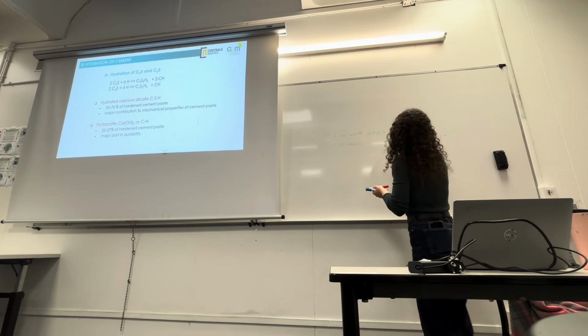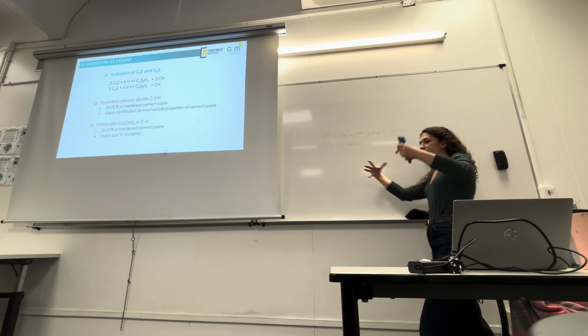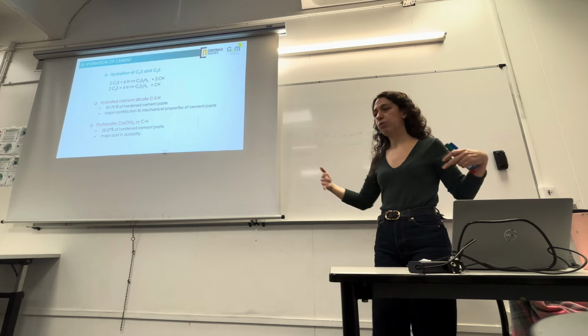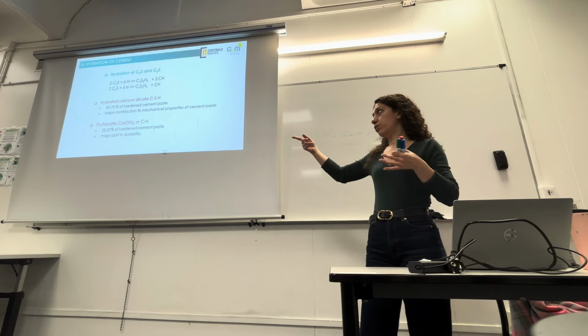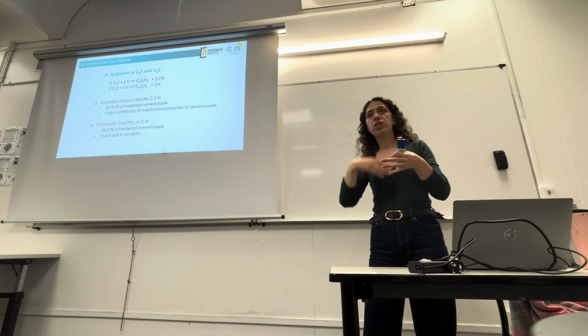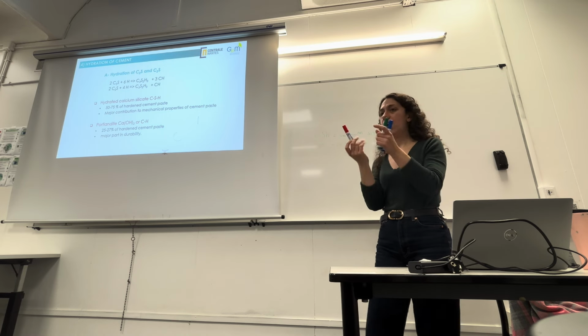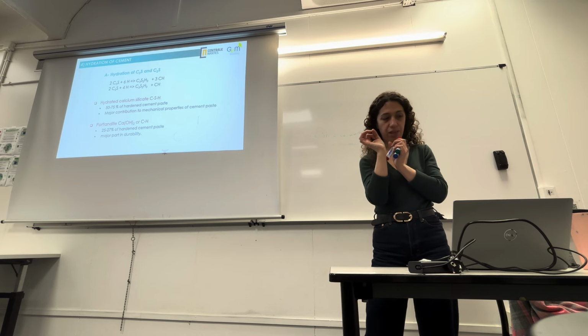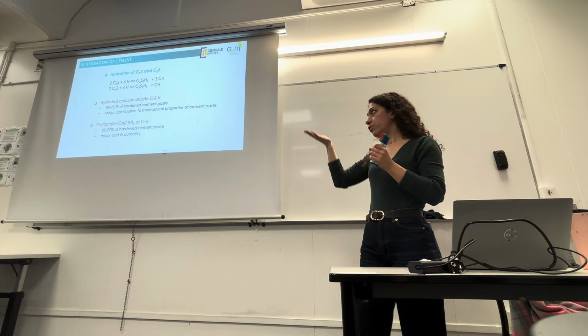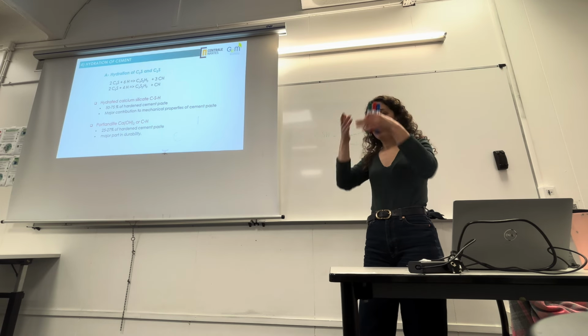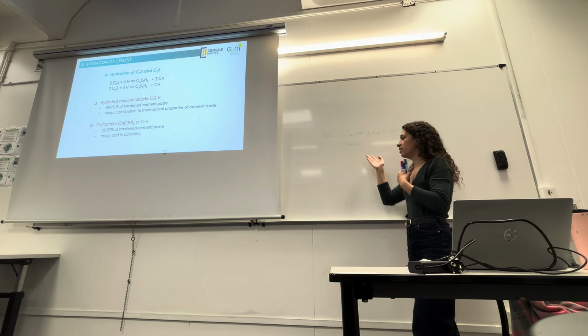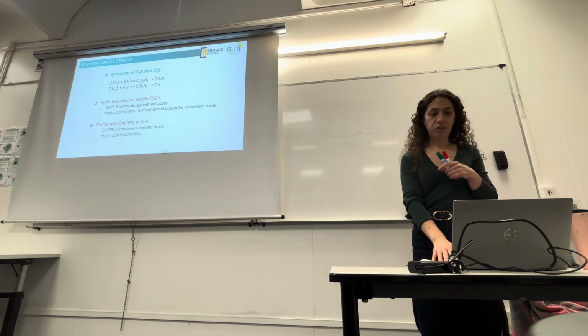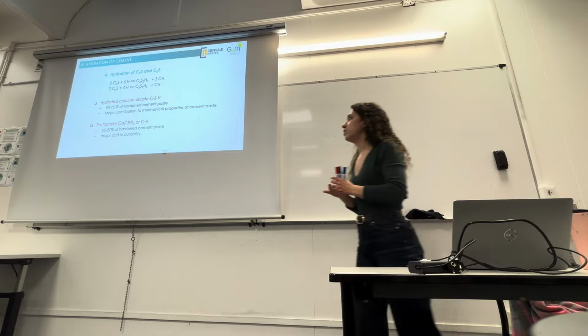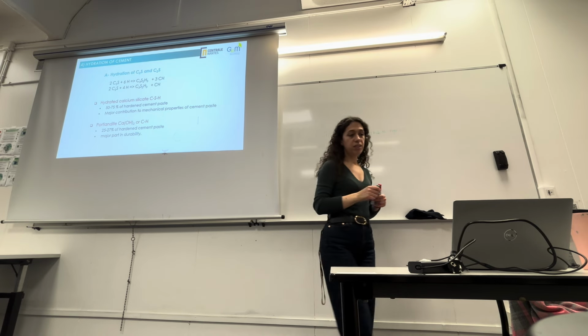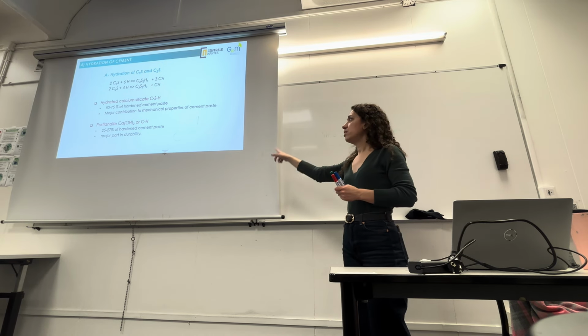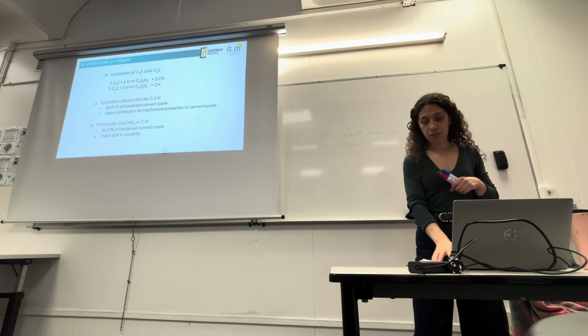So if you put a small cement sample into a very big tank of water, you can almost dissolve all the Portlandite because there is not enough Portlandite to change the pH of all the water in the tank. But if you have a smaller tank of water and a bigger piece of cement, the dissolution of Portlandite can make the pH of the whole solution go higher and reach again a pH of 13, that is good for concrete. Okay, so this is a very important part of Portlandite, a major part in durability. And CSH is the part that makes the most contribution to mechanical properties of cement paste.